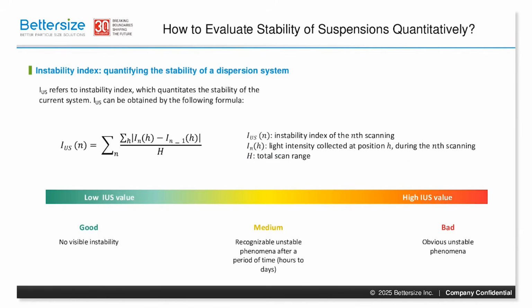But how do we quantify stability? We use the instability index. The instability index is calculated by accumulating the differences between a successive scan and a previous scan. These differences are then mathematically combined into a single value that represents the stability for the whole sample at one corresponding scan. If one scan has a lower IUS value, say 0.5, it indicates that at this moment the system is in a stable status. On the contrary, if the IUS value is larger than 10, you may be witnessing an obviously unstable phenomenon like sedimentation, flocculation, or delamination.